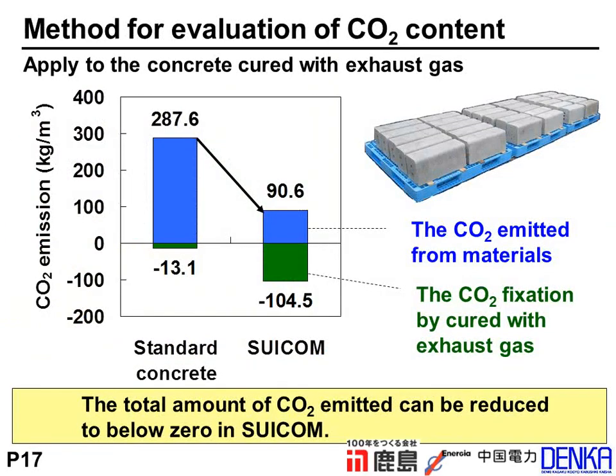So this is the result of the carbon dioxide emission of standard concrete and CO2-SUICOM. This blue bar is the amount of the carbon dioxide emission from the material. You can see that the value of CO2-SUICOM is 90.6 kilograms per cubic meter, reduced by replacing cement with gamma C2S, fly ash, and blast furnace slag. On the other hand, the green bar is the amount of the carbon dioxide fixation by curing with exhaust gas. It was larger than standard concrete. It reached 104.5 kilograms CO2 per cubic meter, which surpassed the amount of the carbon dioxide emitted from material. So the total amount of carbon dioxide emitted can be reduced to below 0 kilograms in CO2-SUICOM.